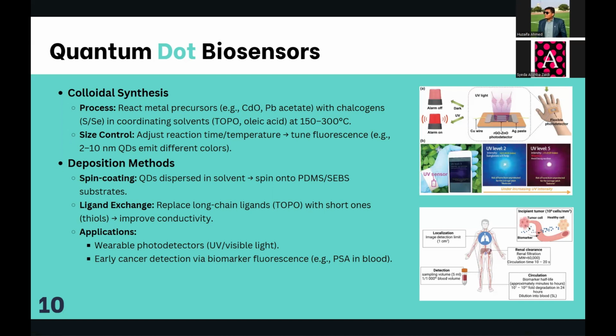Then we have the deposition technique. Spin coating is the number one. Spin coating disperses quantum dots onto flexible substrates like PDMS for wearable photodetectors. Then we have ligand exchange. Ligand exchange replaces the bulky molecules like TOPO with short thiols, boosting conductivity, which is better for signal transmission.